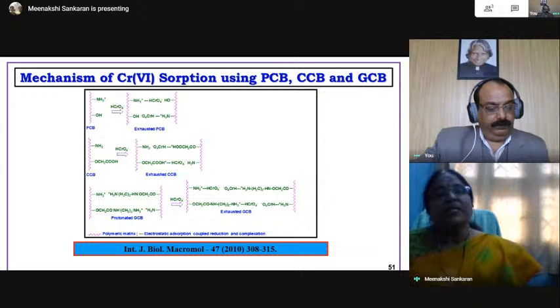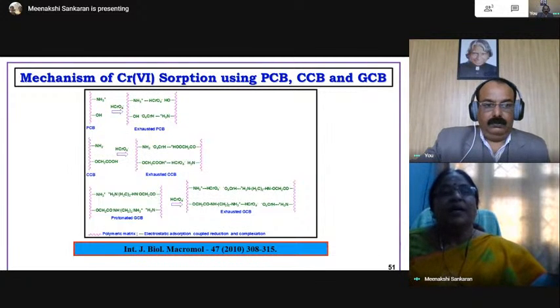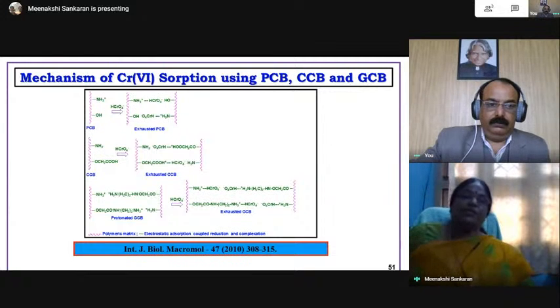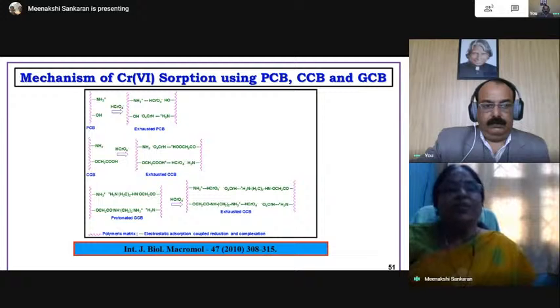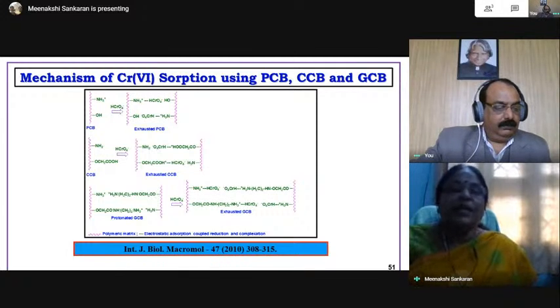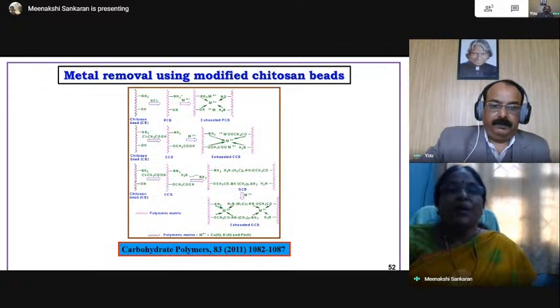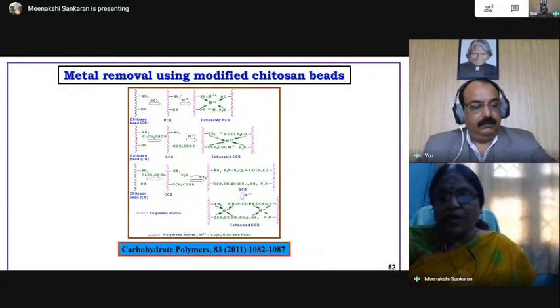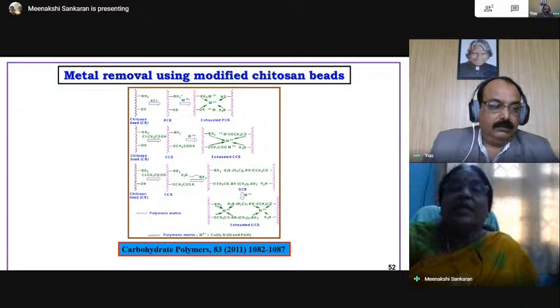Even though it is a metal, when it is in water, it exists as an anion, the chromate ion. So this is a negative ion. So electrostatically, we were able to remove chromium from drinking water as well as the effluents. Like for fluoride, we have used protonated chitosan beads, carboxylated chitosan beads, and metal-loaded chitosan beads. When we introduced positive groups into chitosan, they were able to absorb fluoride electrostatically. And we have also introduced metals in order to enhance its positive charge, which in turn removes fluoride and chromate ions by means of electrostatic interaction.